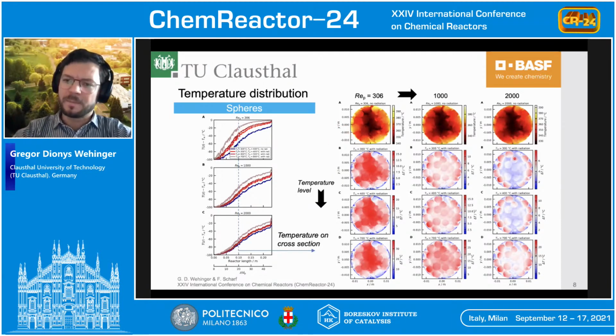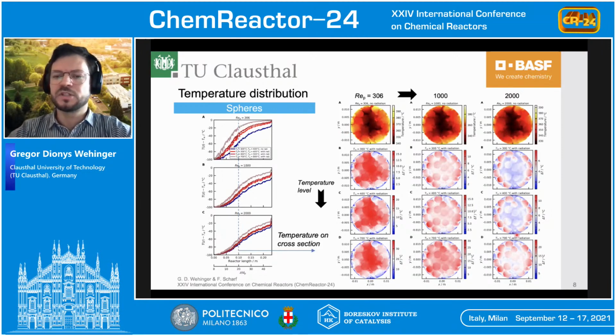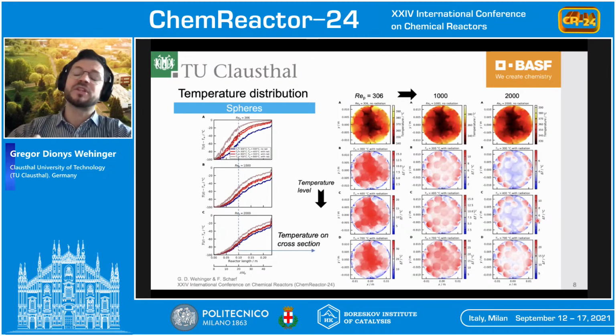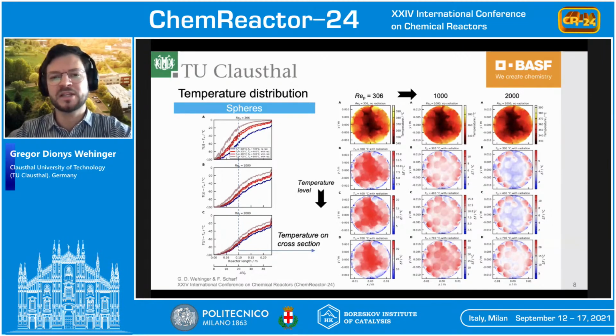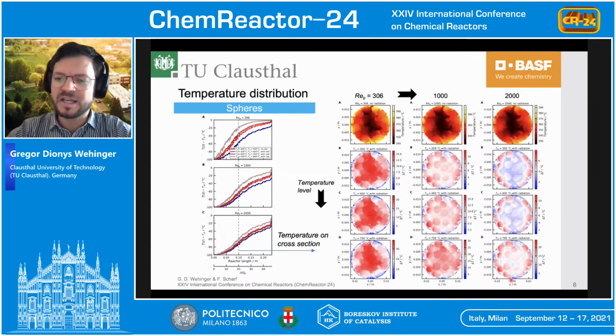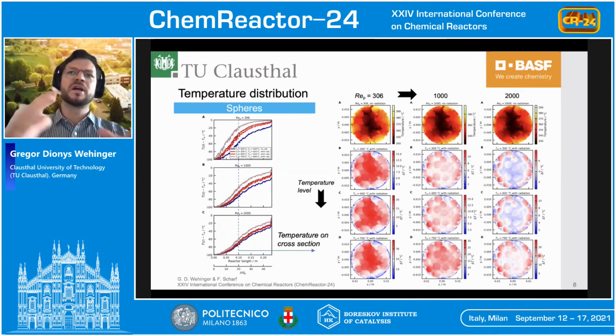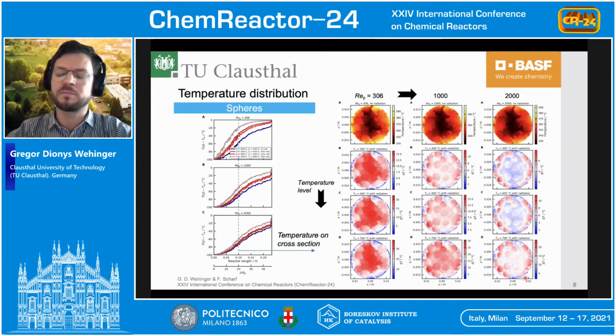And now on these rows, you see for the different temperature levels the difference between the scenario with radiation and without radiation. And as you might notice, we see very large differences. The largest one is around 40 Kelvin for the scenario with lowest velocity and highest temperature range. On the other hand, we also can see for the high velocity range that the effect of thermal radiation is highest very close to the wall. So the hot wall is influencing the near wall particles.